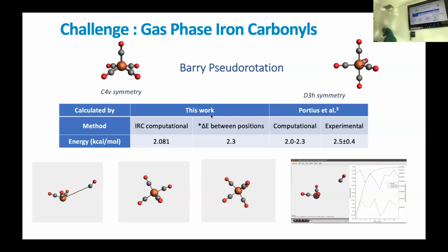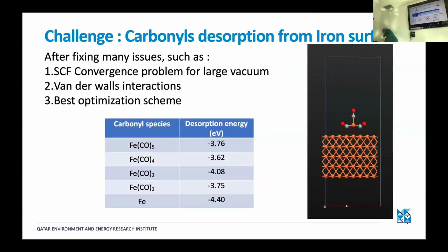Another challenge is that the removal of CO molecules in the gas phase also needed to be taken into consideration, along with the subspecies of carbonyl: Fe(CO)5, 4, 3, and 2, assuming there is sequential addition of CO molecules. You see here the simulation of the desorption of the molecule. This requires an even larger slab than what we considered for sulfur and for CO alone, because the molecule itself is bulkier. So we had to trade off a little and reduce the number of layers.